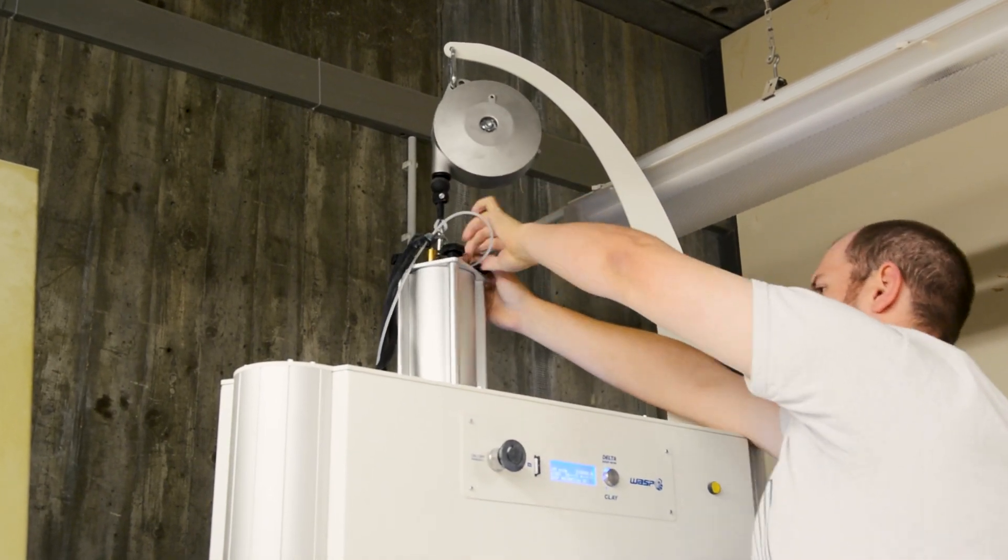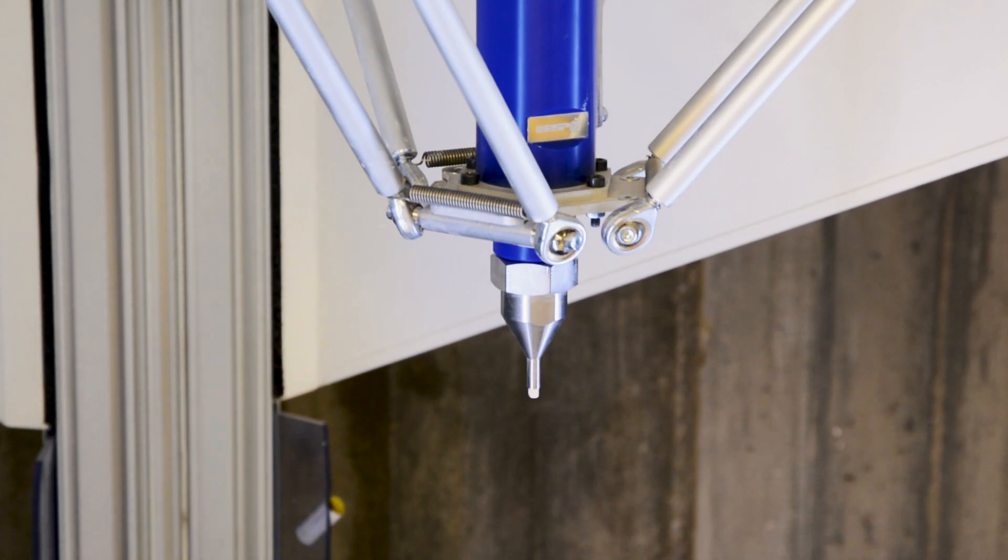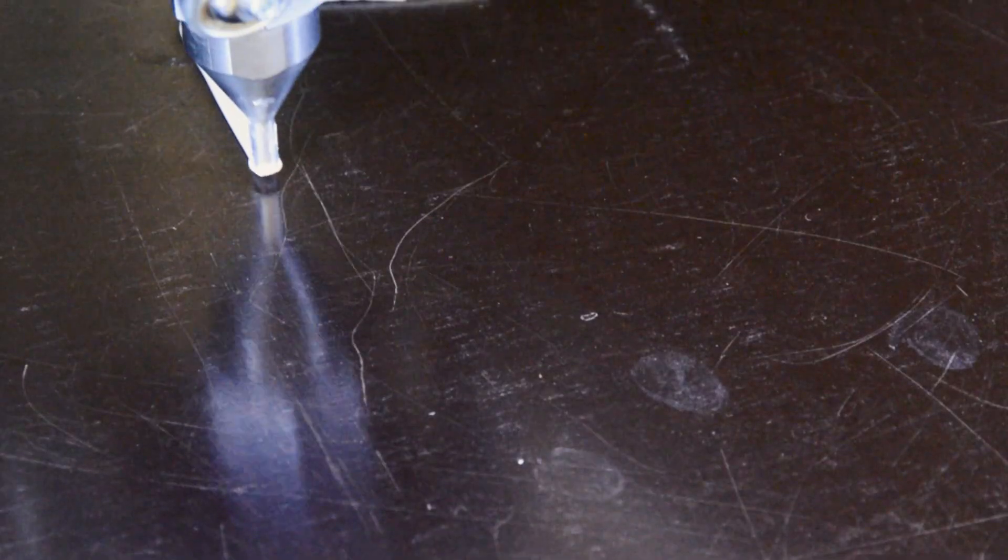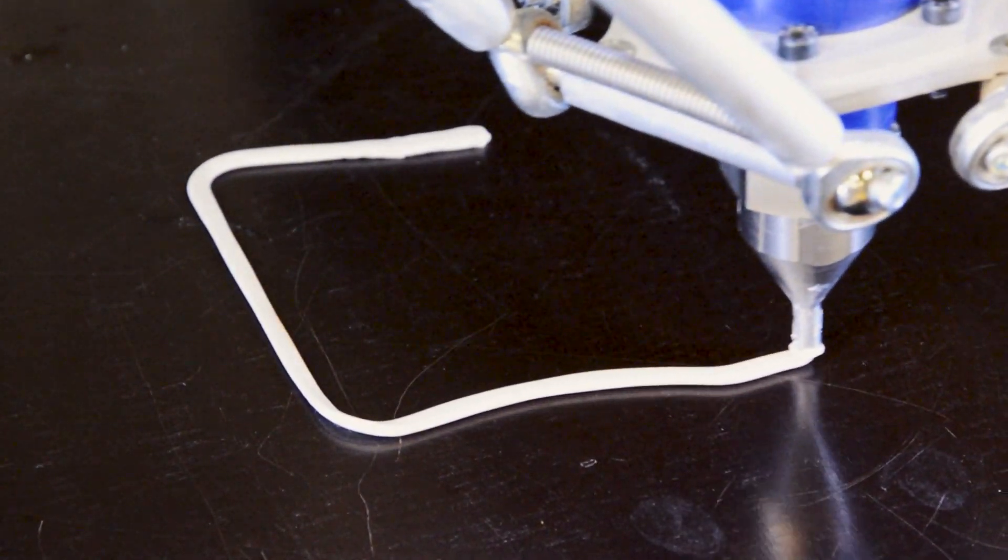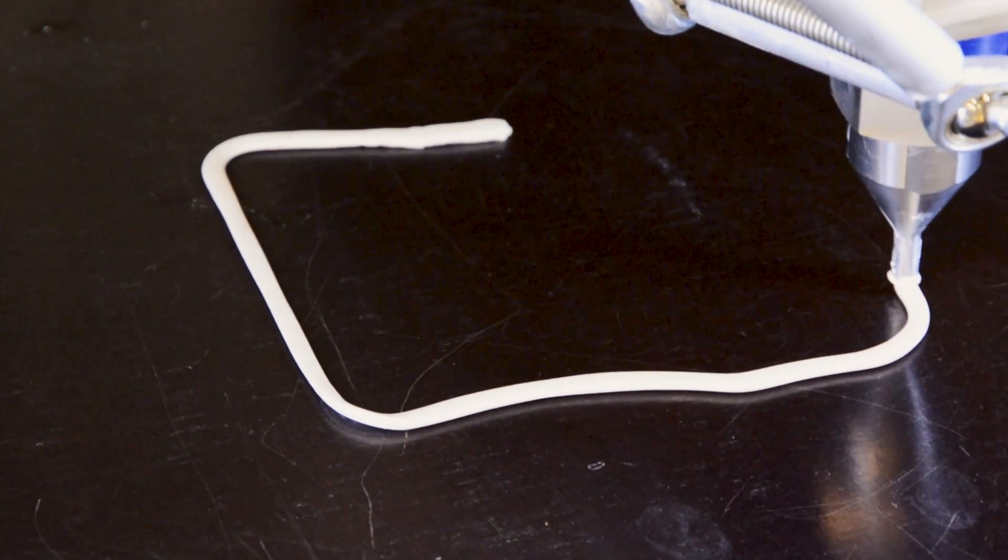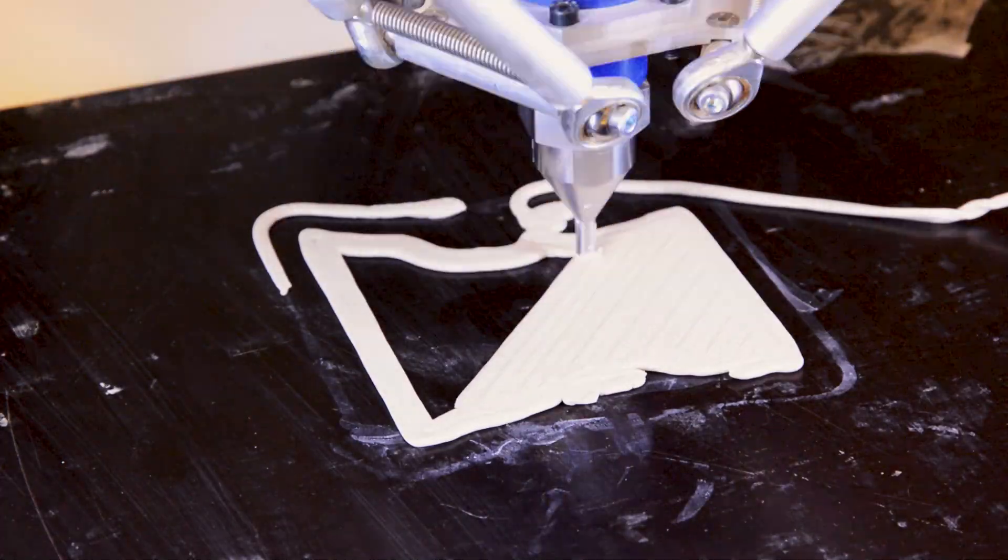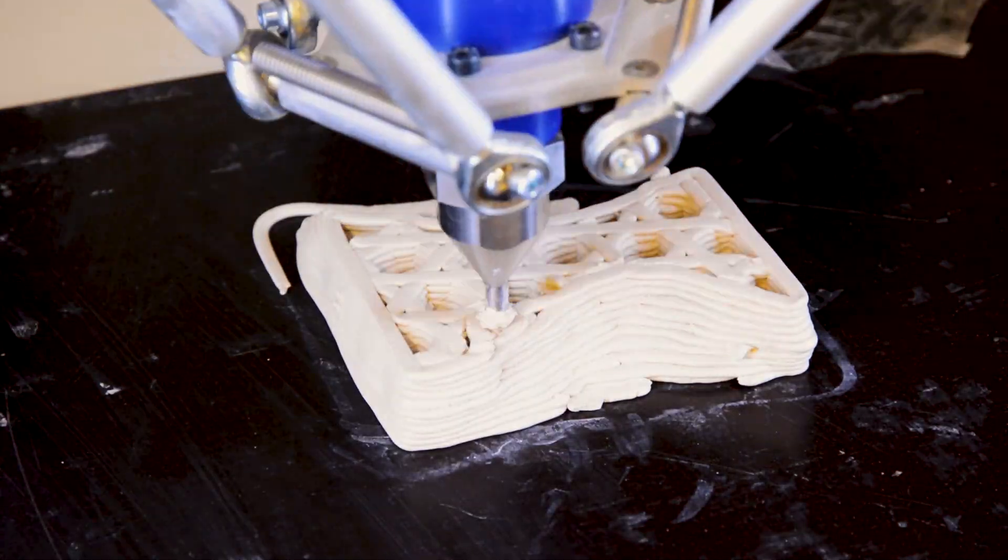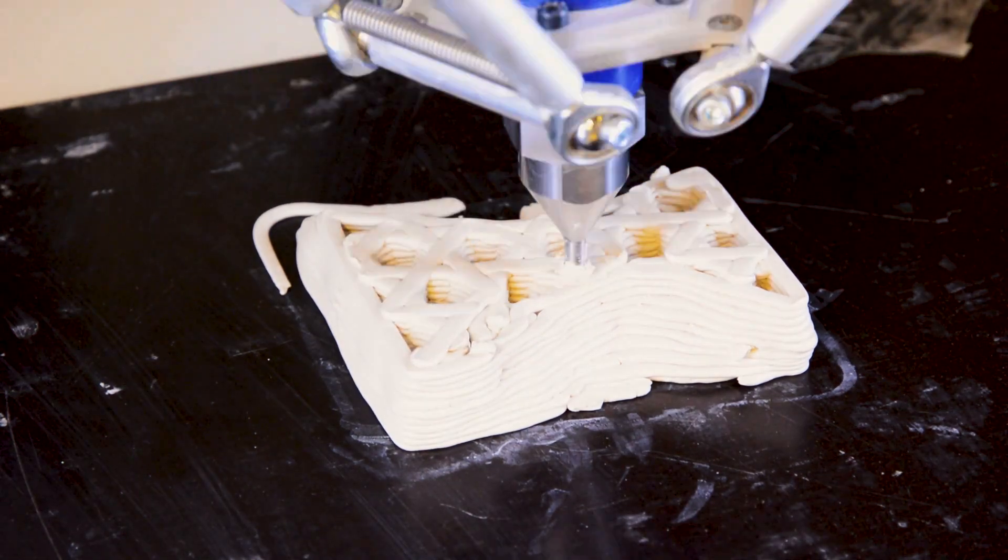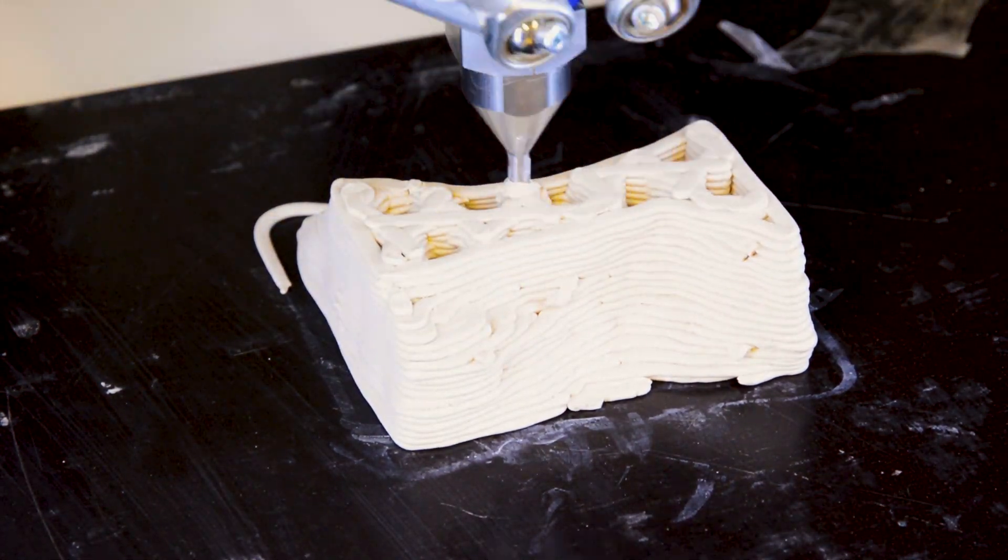Furthermore, we aim at keeping these recipes as simple and as virtuous as possible, by radically restraining the resort to additives. The rock tower has been printed only with clay and water. We print with an off-the-shelf clay printer, robust enough to handle the variety of recipes we have been experimenting with. It also is small enough to be easy to transport.